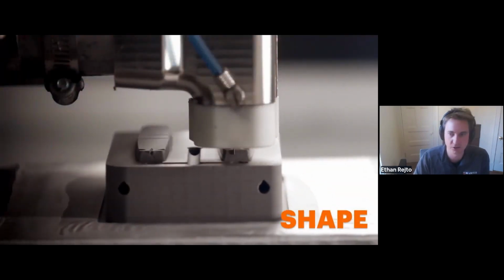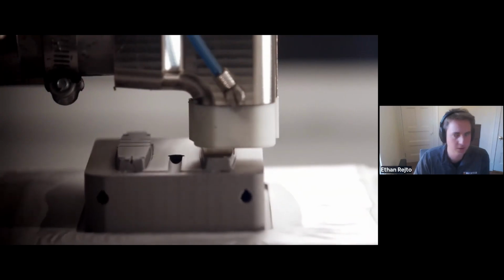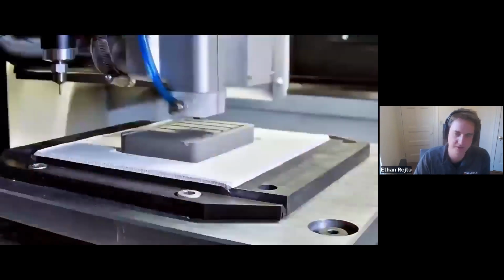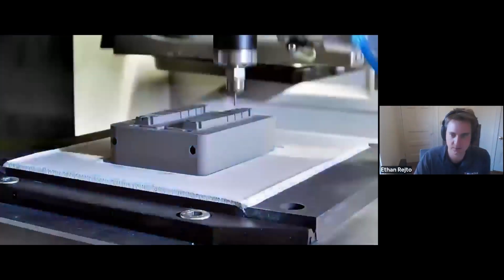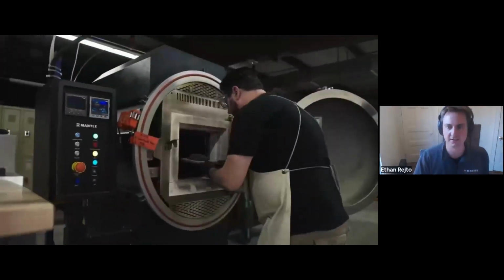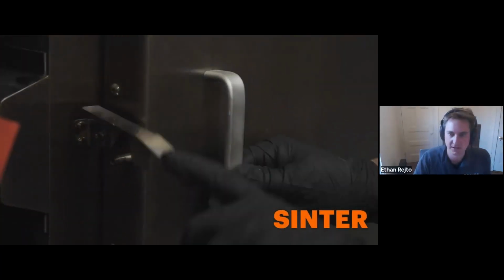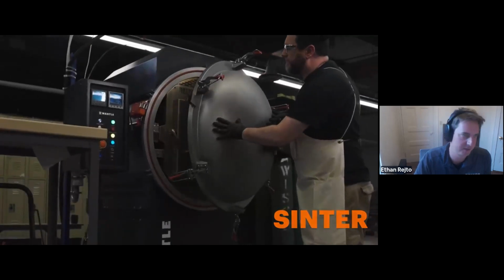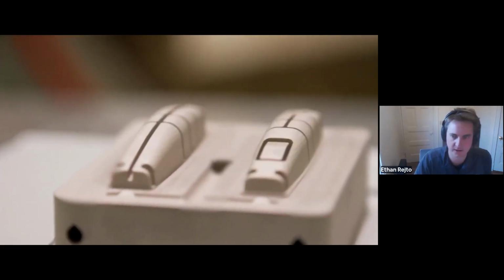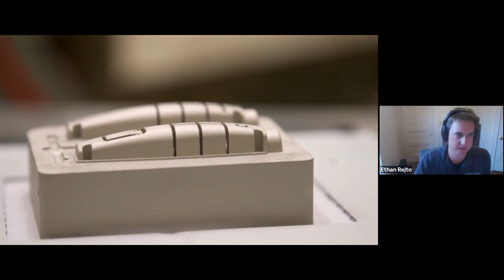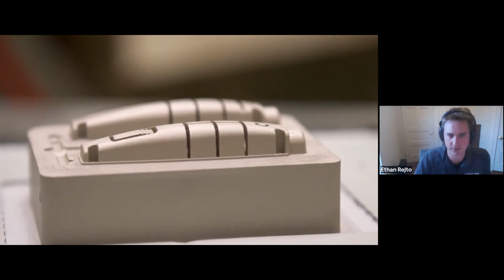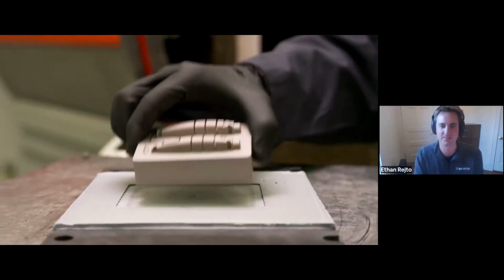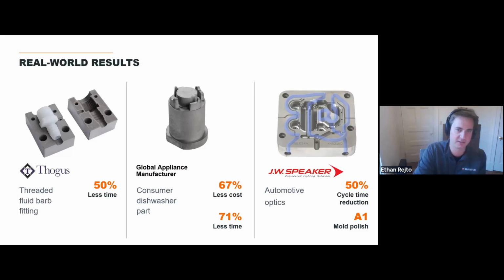It also enables us to use some really, really small cutting tools because the force on the tool is very, very low because it's a layer at a time. The smallest cutting tool we're using today is a 6 thou ball end mill. You can see it's then placed inside of a furnace. That furnace is going to take anywhere from 24 to 42 hours, depending on the size of the part. And then what comes out is a dense, strong tool steel component. So hopefully that helps understand the process a little bit. It's a very unique process where we're printing, drying, and machining every single layer.